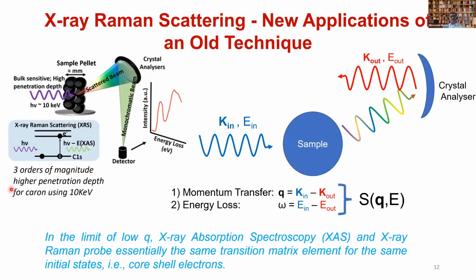Why am I emphasizing bulk? Because in the case of carbon, you have three orders of magnitude higher penetration depth using 10 keV, instead of using the carbon K-edge of 280 to 300 electron volts. So that's what we have done. We have used this technique successfully at ESRF and APS. There are many different places that you can use.